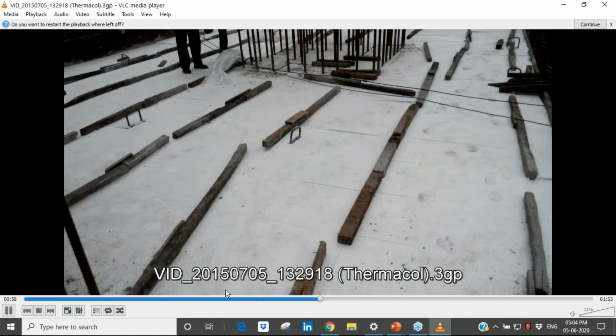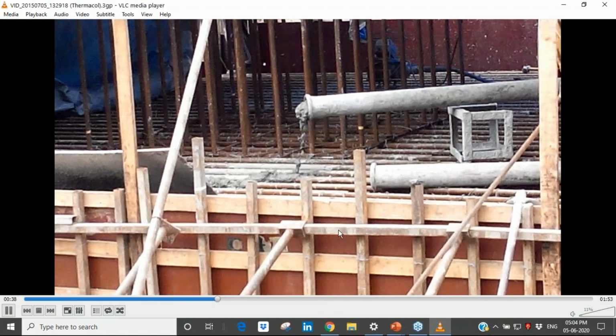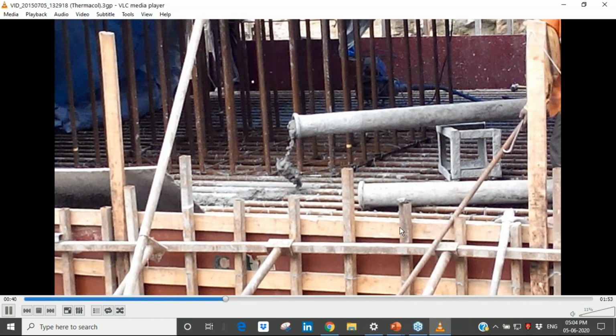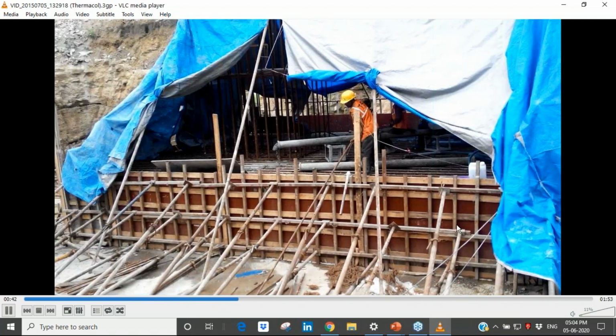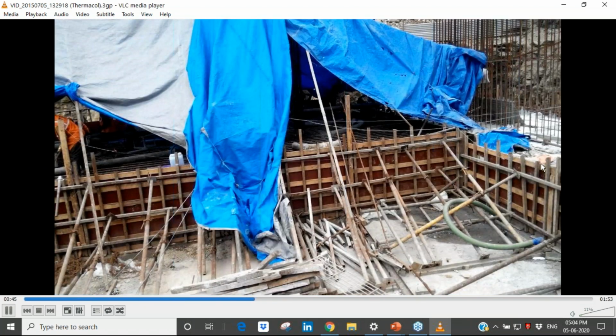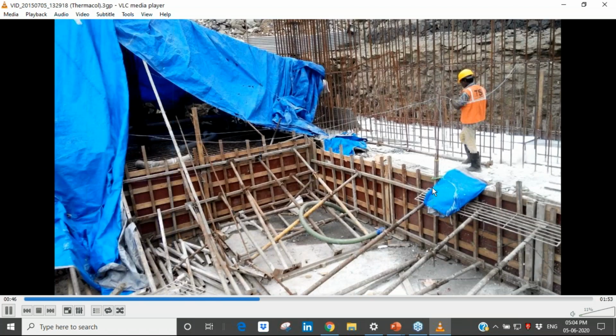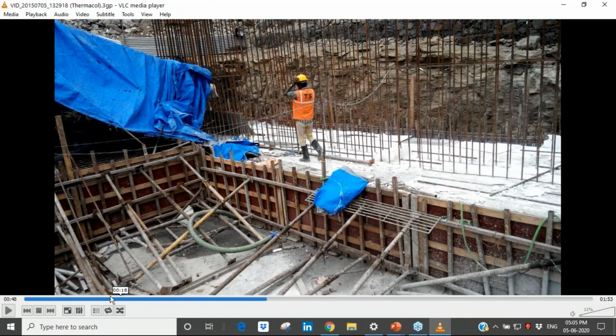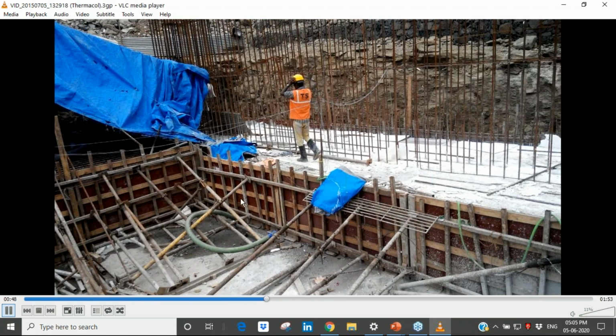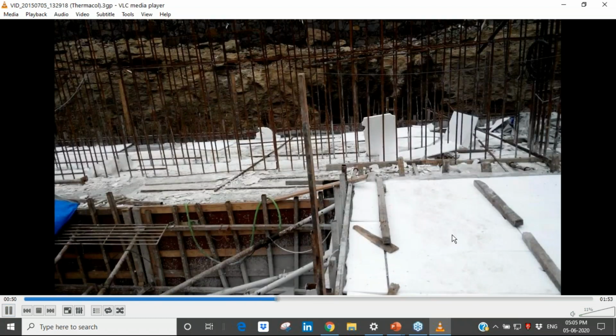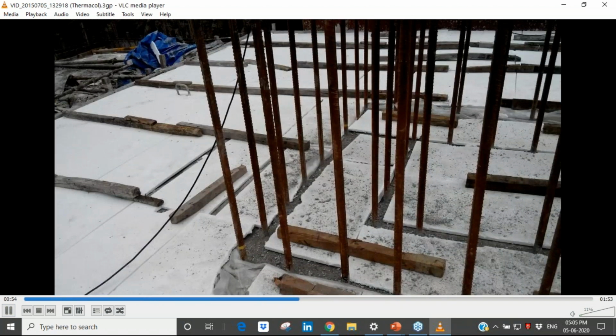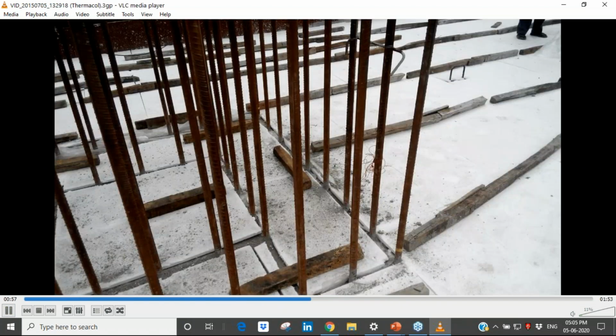You can see here, this is the third pour of the raft of one of our high-rise buildings under process. And you can see the first pour here. If this was cast, you can see absolutely no curing is done for 7 days, and only plastic sheet and Thermacol insulation, with Thermacol on the vertical shutters, are intact. That you can also notice. And in the second pour, where I was standing and taking this clip, you can see Thermacol is doing the job of insulation. So we are controlling the gradient within 20 to 25 degrees as specified by the consultant.